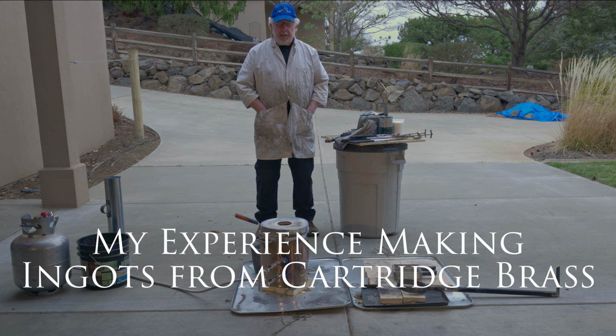Now, this crucible has about 50 melts in it, so it's got a bunch of crap inside of it. And this is what that would look like when it was new. Nice. This is, of course, the furnace. This one has two burners, a lid, and I'll show you in a while that there is an insulating brick in the bottom of the furnace.